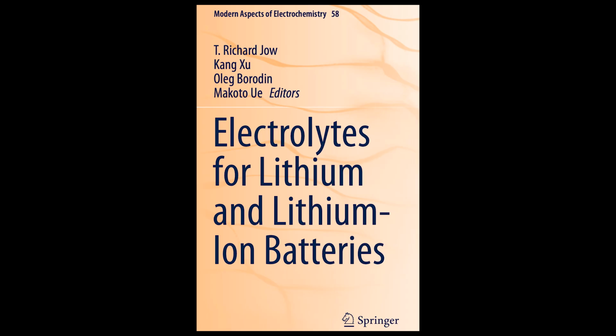It was further found by Saft in 1994 that adding just small amounts of VC to carbonate-based solvents helps to form a stable, protective SEI layer on high crystallinity graphite anodes. Okay. This layer forms at relatively high voltages and prevents the continuous decomposition of the electrolyte, which would otherwise just consume the electrolyte and lead to rapid battery degradation. Mitsubishi Chemical also published significant work on this in 2004. So it's a key ingredient for building that essential protective layer on the negative side of the battery, especially for graphite. Exactly, a cornerstone additive.